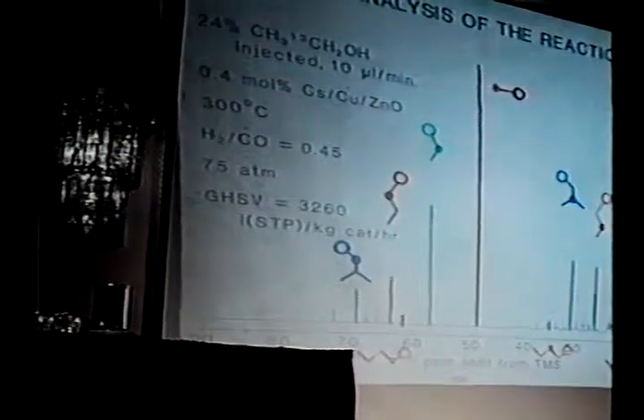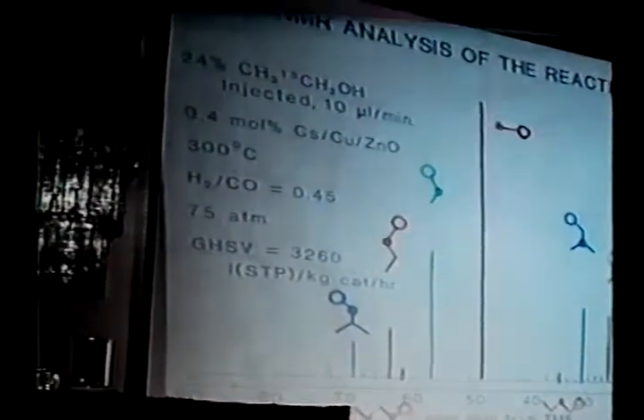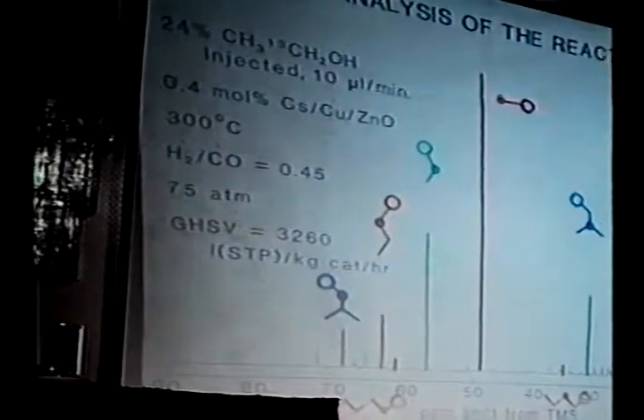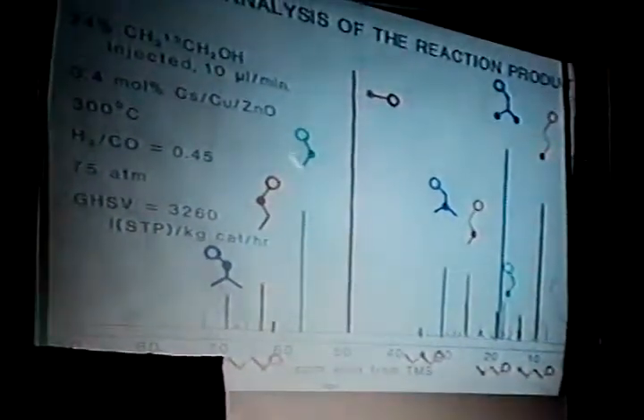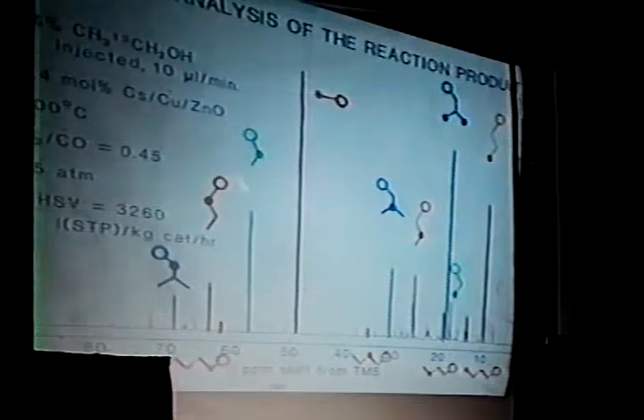The comparison that I wanted to make with the copper-zinc catalyst is displayed here. The reactions are entirely opposite here, and the flow of labels is entirely opposite too, and the product composition is entirely opposite to the molybdenum disulfide with cobalt or without cobalt. We've done many of these injection experiments, and I'm pointing out only one that is really crucial to the understanding of the C2 to C3 step, which on this catalyst is the overwhelming synthetic step. If one injects ethanol, this is oxygen, this is the labeled carbon, and this is the unlabeled carbon of ethanol. Remember that the C13 is here. This is the other label of ethanol, which is low. This is the high label of the inner carbon.